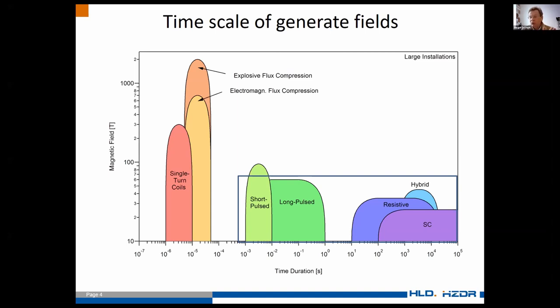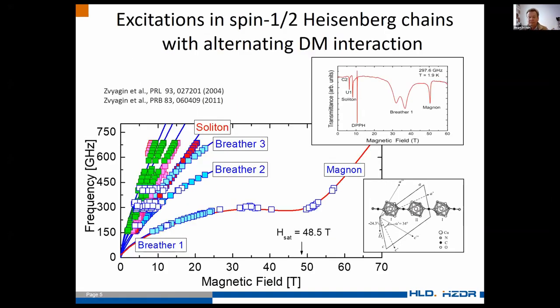So what we are doing in Dresden is using short pulse magnets in combination with superconducting magnets, so we can go up to approximately 70 Tesla. Just to illustrate what we can do with pulsed fields and tunable frequencies, I would like to show you the frequency-field diagram of magnetic excitations in spin-1/2 Heisenberg chains with alternating Dzyaloshinskii-Moriya interaction. The idea is very simple. If you're looking at quantum magnets, it's better to start with something simple, and the simplest model system is the spin-1/2 Heisenberg chain.